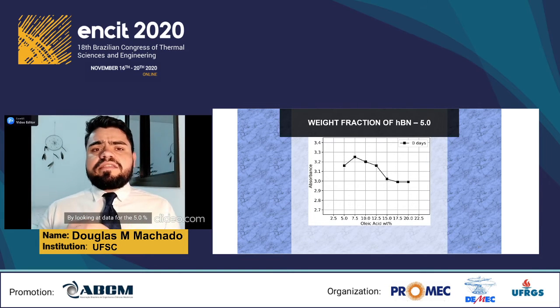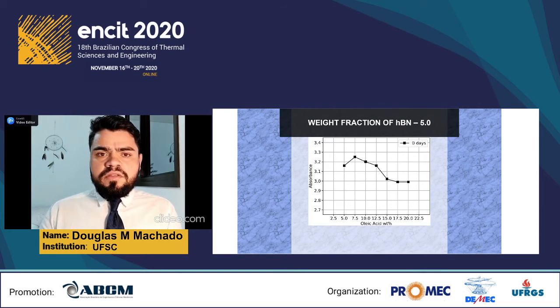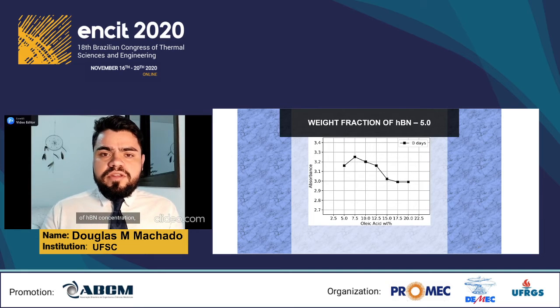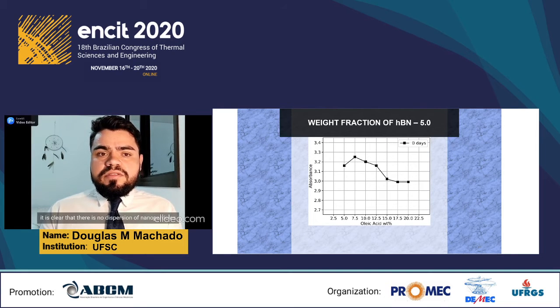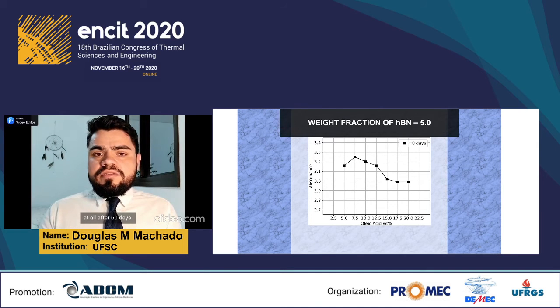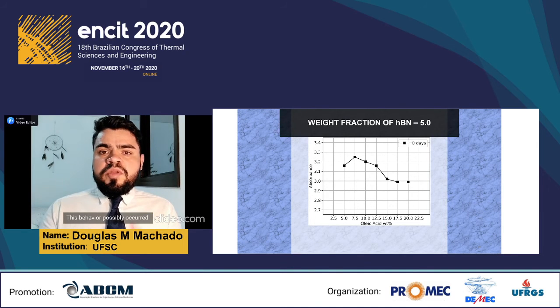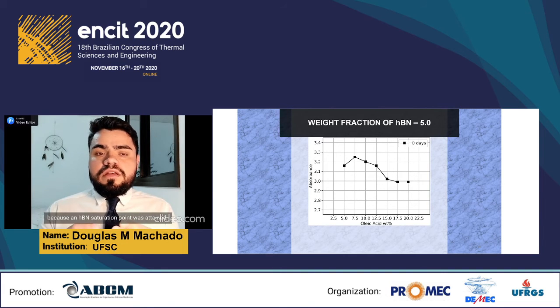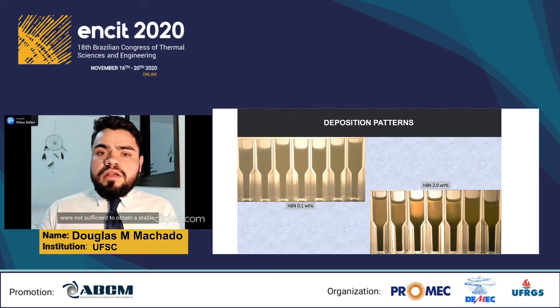By looking at data for the 5% hBN concentration, it is clear that there is no dispersion of nanoparticles at all after 60 days. This behavior possibly occurred because an hBN saturation point was attained, so the oleic acid concentrations considered in this study were not sufficient to obtain a stable and homogeneous sample.